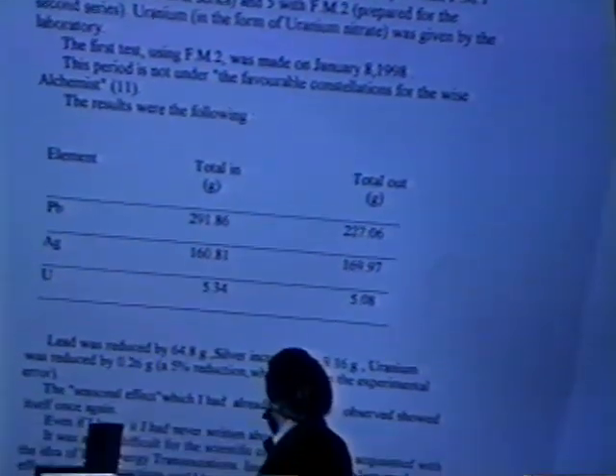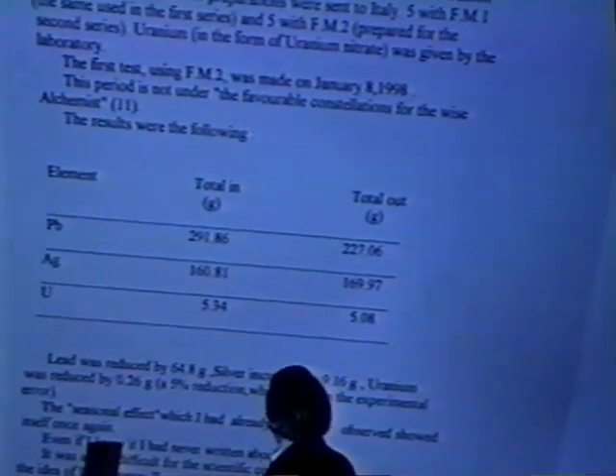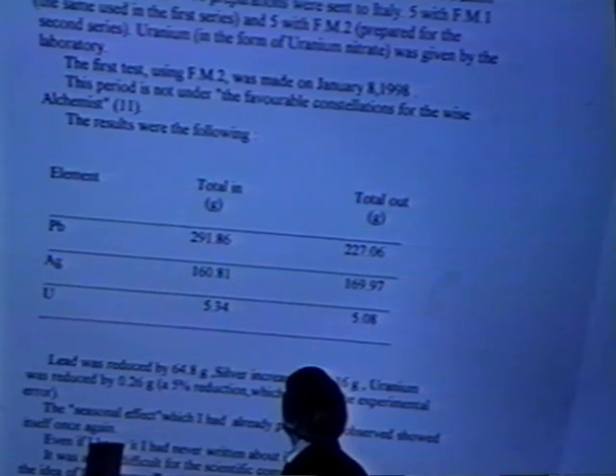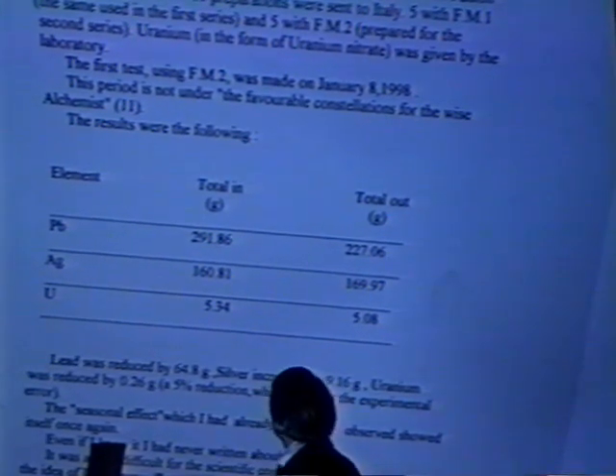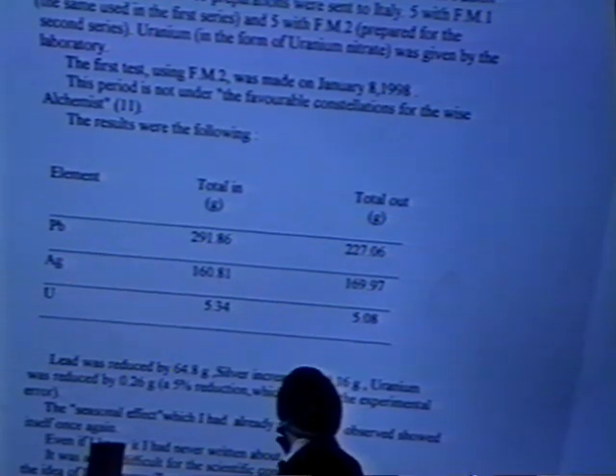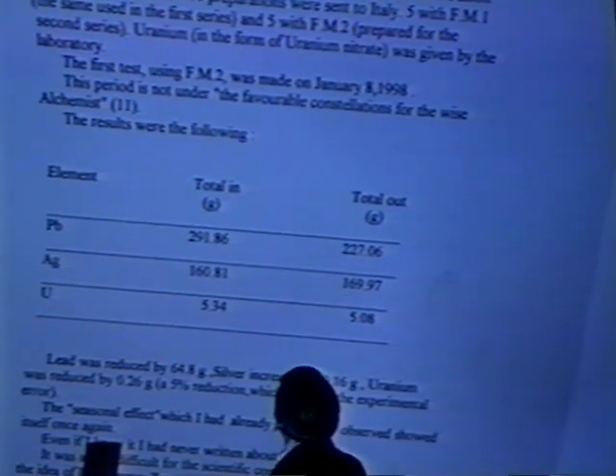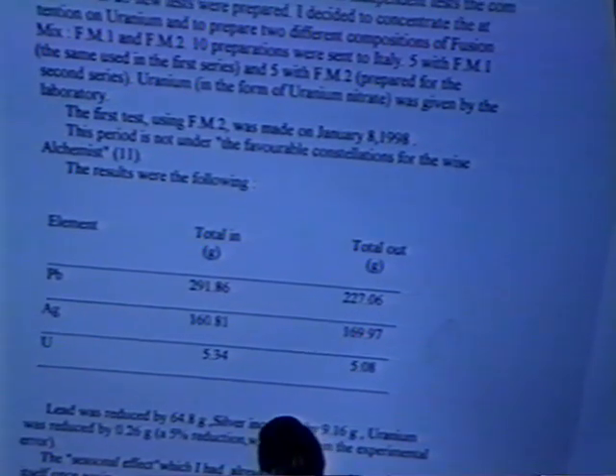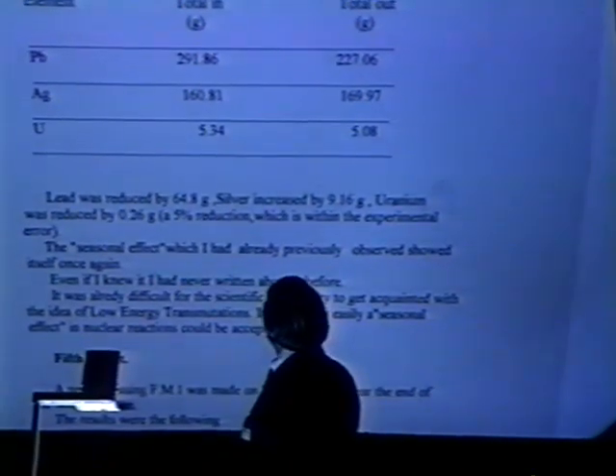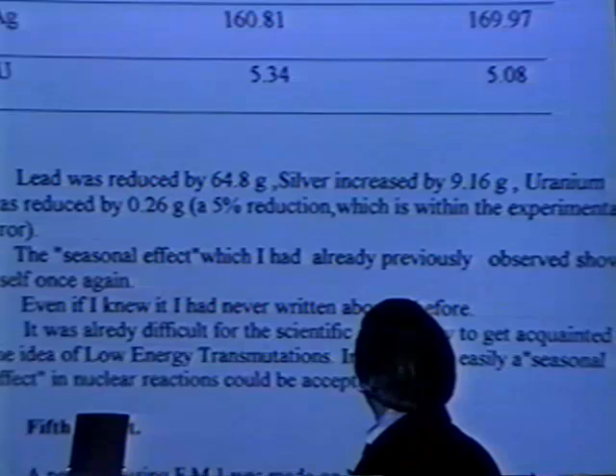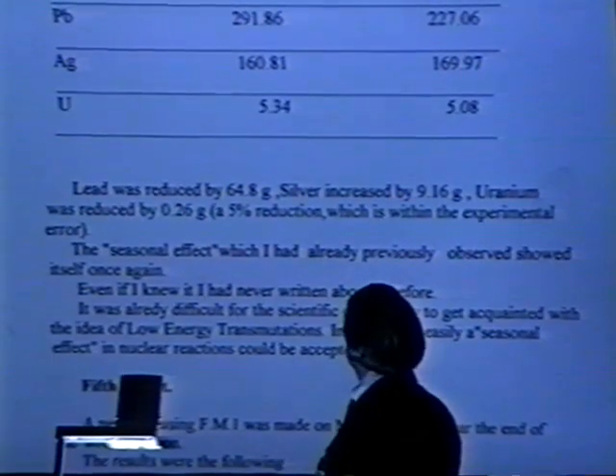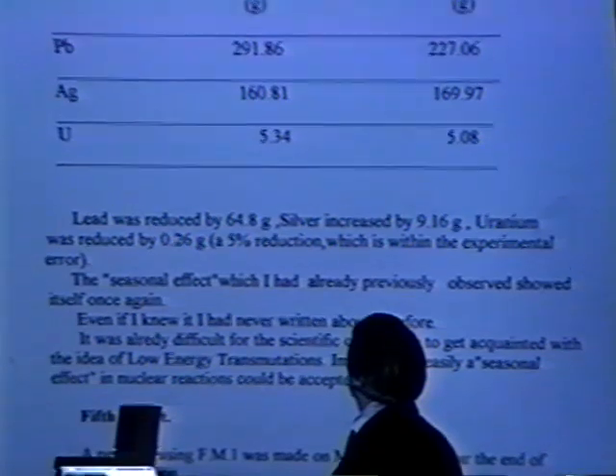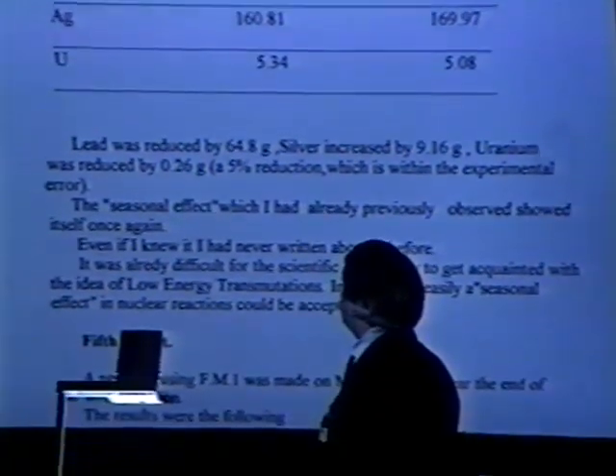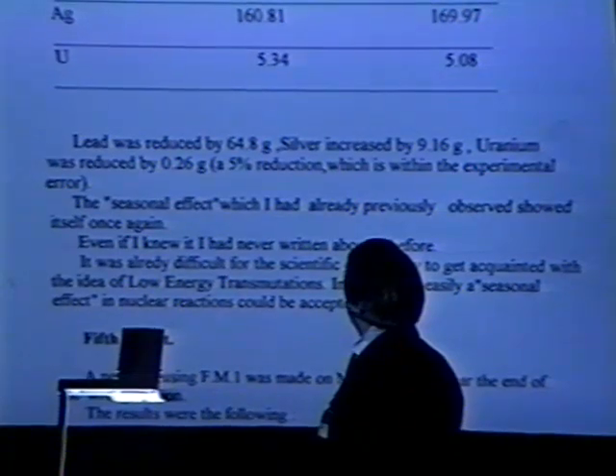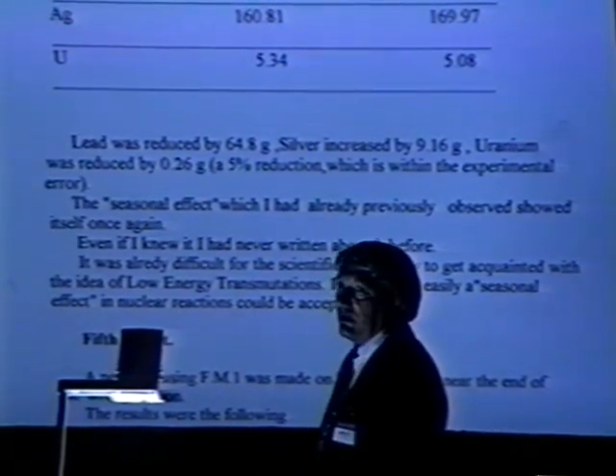After the results, I decided to concentrate attention on uranium and to prepare two different compositions of fusion mix, which I called FM1 and FM2. The same preparation was sent to Italy, and the results of the test follow in the report. Lead was reduced by 64.8 grams, silver increased by 9.16 grams, and uranium was reduced by 0.26. But as we can consider the experimental error about 5%, it was considered a slightly new result. It was important for me because I could see that the laboratory can really measure the uranium.